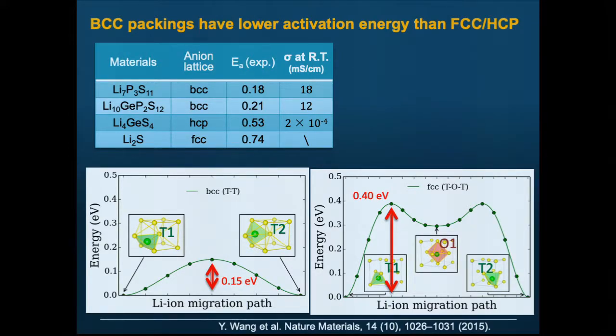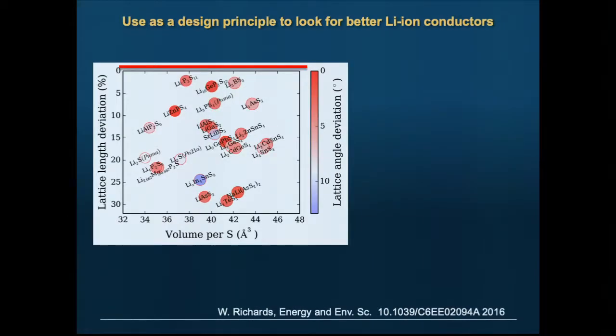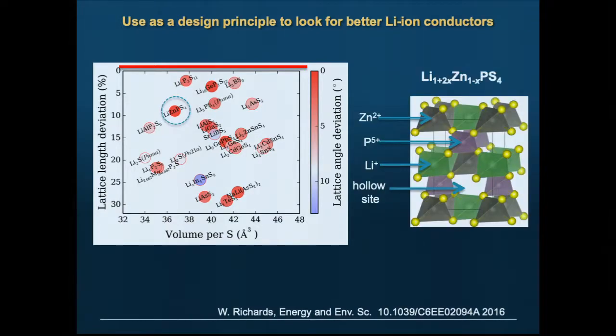So this is a pure anion effect. There's nothing else around. And indeed, if you look at some really good conductors like LPS and LGPS, they have BCC anion backbones. If you just take everything else away, the anions show a BCC structure. Whereas if you look at some worse conductors, they have HCP or FCC backbones. So this was a key insight, because now you go, I'm just going to look for more compounds with BCC backbones, right? And so you search through the ICSD, you code up a few algorithms to look for how the anions are packed. And we found one that nobody ever thought about, a lithium zinc thiophosphate, or LZPS as we call it.